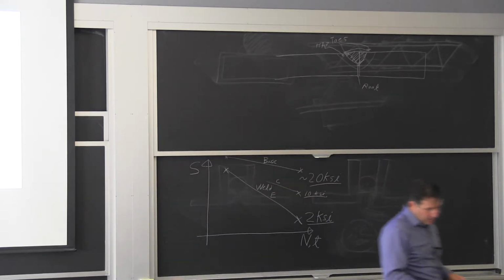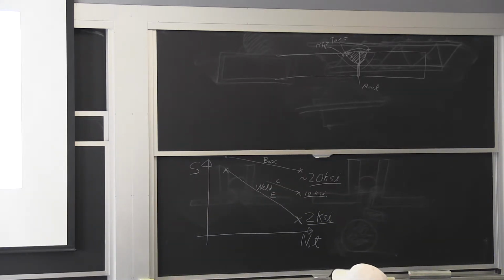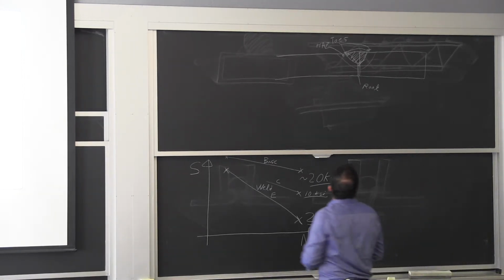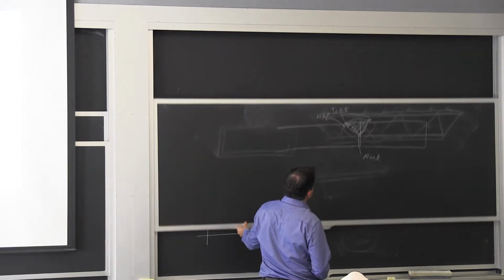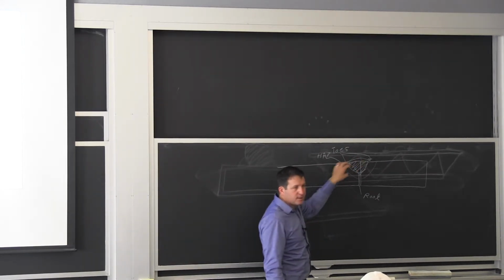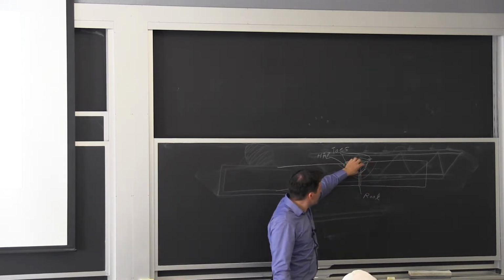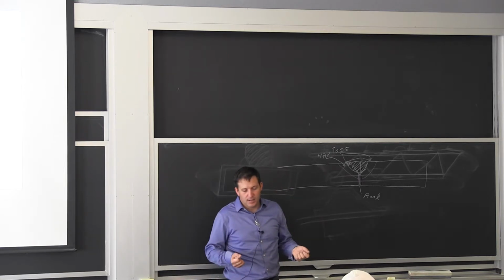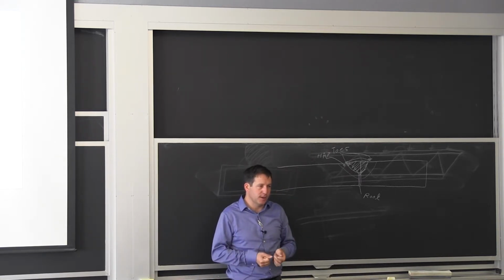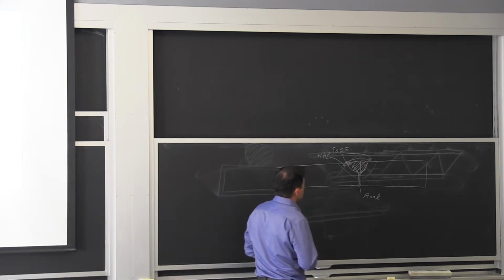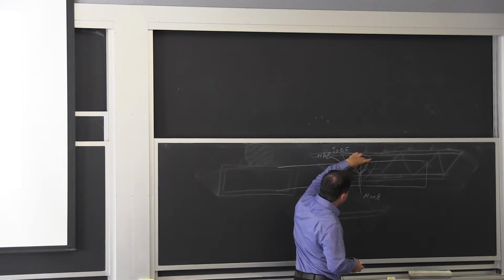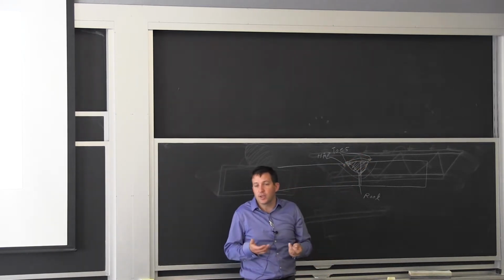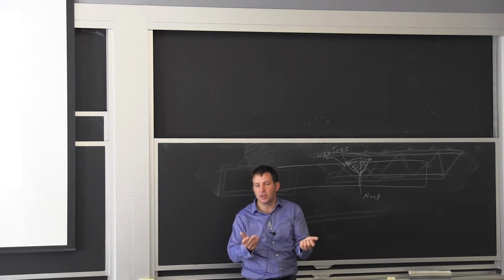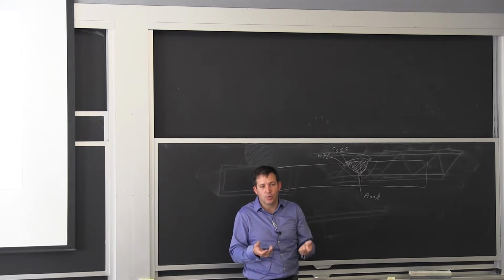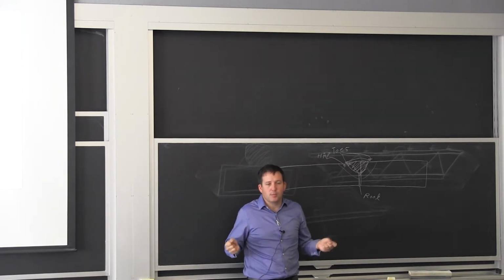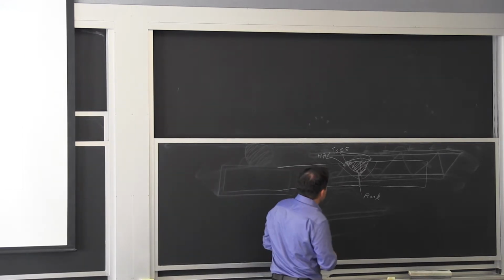Now, why does it make such a difference? If you weld, you're melting the steel. So if we go back to this here, this is really, really hot, and this is cold. So when I'm cooling off, this very hot zone of steel is going to be shrinking. It's just the thermal contraction when you're cooling. It's solid here, it starts to pick up strength. When it's liquid, nothing is really happening. But when it starts picking up strength, when it's solidified and it's cooling, it will be really pulling on the material. And what you're left with at the very end is tension.